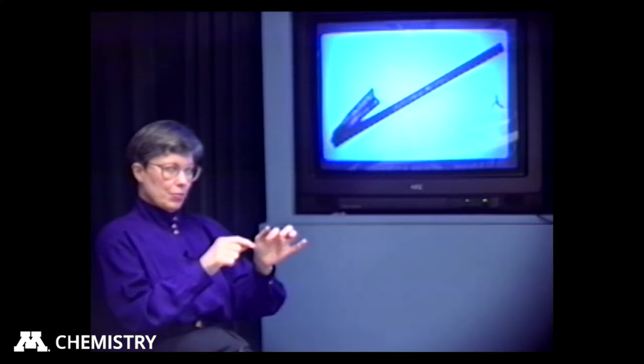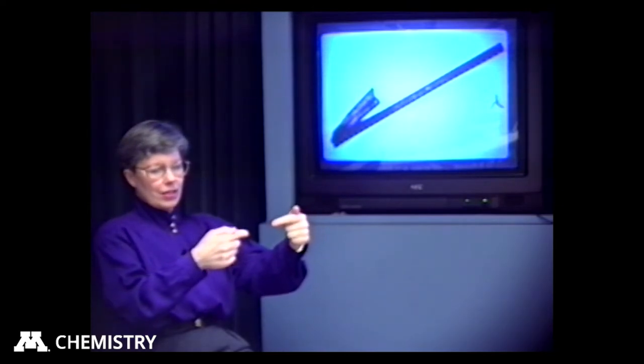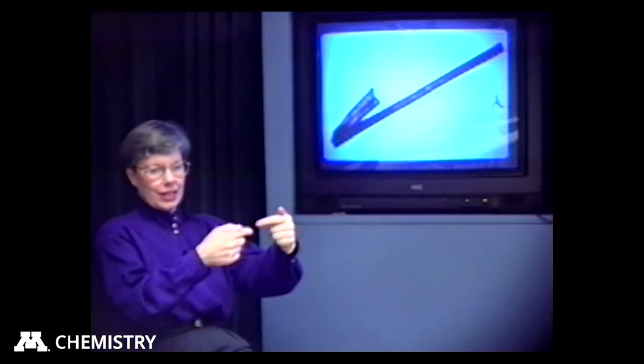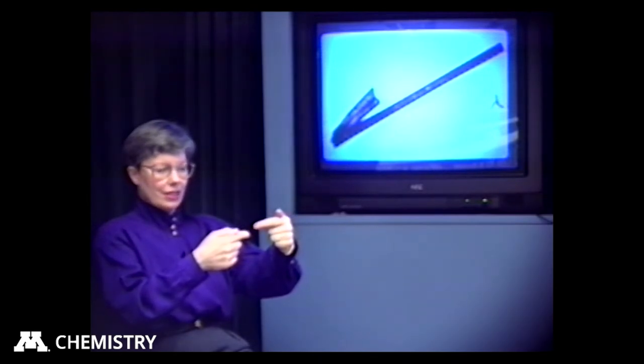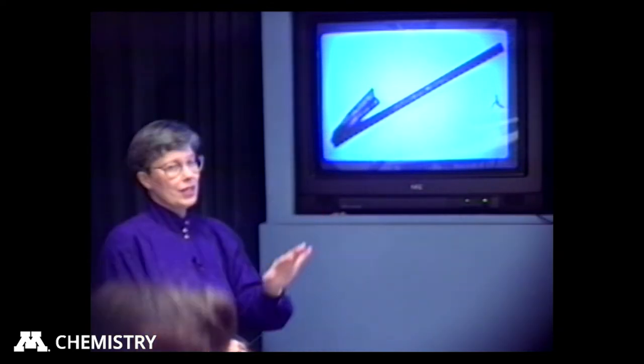And what usually happens is that as the edges of that drop start to dry out, needles of glycine start to grow into the center of the drop. But if you keep watching it, all of a sudden, those needles will transform into blocks. And you can see that solution-mediated phase transformation very clearly. The other way to watch the glycine crystal change is to put it in a small test tube. And the first crystals that come out just on sitting at room temperature probably will be the long needles. And then a half hour or so later, you won't have any needles. You'll have just the block-shaped crystals.